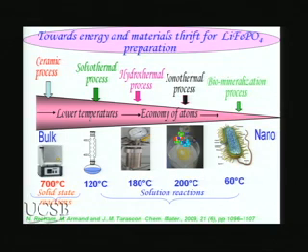So if I look at the trends here in terms of electrode materials, this is, for instance, the famous lithium iron phosphate, the most praised material nowadays in lithium technology, which is a mineral and which was disregarded 20 years ago because of its poor electronic conductivity. So in this case, you can see that we cannot use this material as made, but we really need to transform it into nanomaterials. And of course, what is very important as a chemist is to find the best way to expedite and to find very low-cost processes. And what we have been doing, we play with all our chemistry knowledge in order to develop different techniques, as indicated here, when we move from the classical ceramic process to some low-temperature solution techniques, during which we both have an economy of atoms and also decrease temperature. So we have a kind of eco-efficient process.